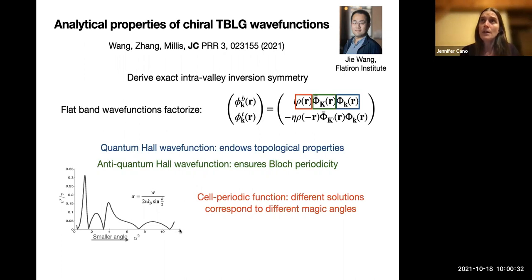But you could also look at twisted transition metal dichalcogenides, and there the physics is a little bit different because you don't realize magic angles. You realize a continuum of effects. I don't know if you've studied this or not, but in the twisted TMDs, you basically get a W shape. You don't have a flat band, but it has a region which gets pretty flat, and you have a Van Hove singularity, but you don't have a magic angle. And so there, I expect that it might be a different story.